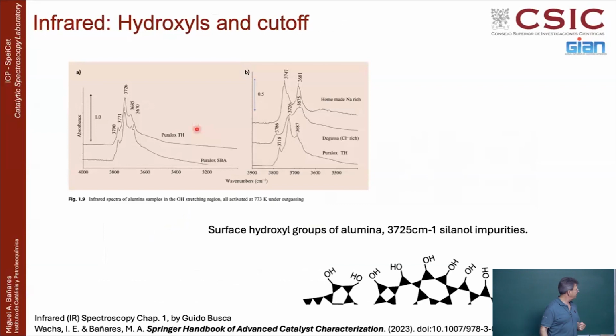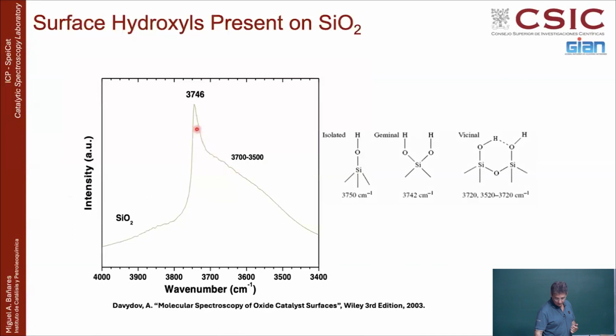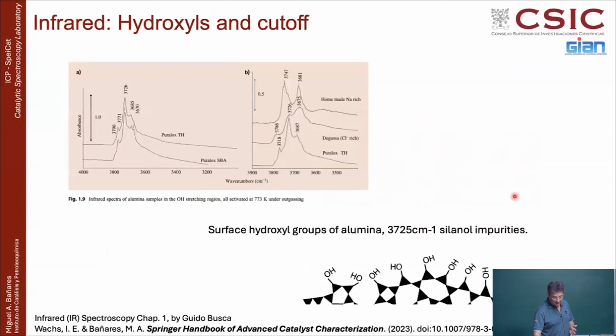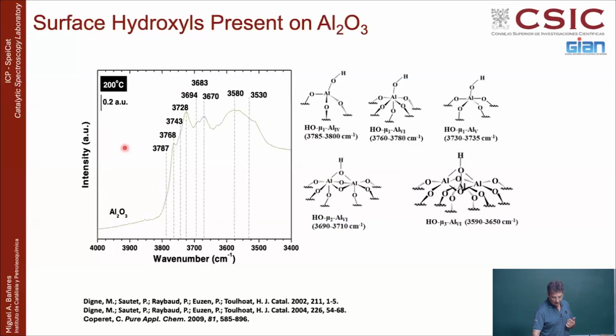You can see many things showing that interaction between the hydroxyls. In the case of silica, eventually you can get geminal or vicinal ones, and that will result in a lower and lower frequency. This is not that common on silica, except on the more hydroxylated one, but this is increasingly common in the other oxides. And that's why you get a lot of bands, and not only a single band for the hydroxyl group. Here you have, for instance, surface hydroxyl groups on alumina.